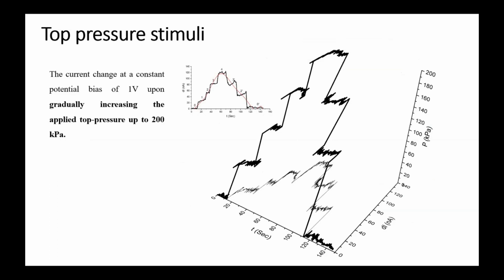The second mechanical response is pressure. When we press on top of the latex, we can see that we change the conductivity and the current according to the strength of pressure. What we have here is applying 1 volt. The current changes at a constant potential bias of 1 volt upon gradually increasing the applied top pressure up to 200 kilopascal.